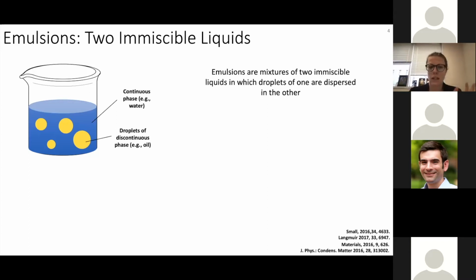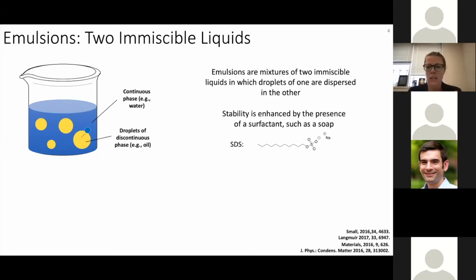So these are typically kinetically unstable systems, and we get the coalescence of the droplets in the macrophase separation. But we can decrease the interfacial energy and increase the kinetic stability or create steric stability by adding in surfactants. A lot of times we think of surfactants as these amphiphilic small molecules where we have a hydrophobic tail in the oil and then the hydrophilic head group at the water. In this way, we can stabilize droplets and prevent that macrophase separation. You can also use polymers as surfactants as well.